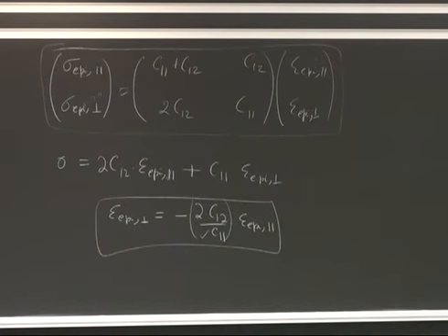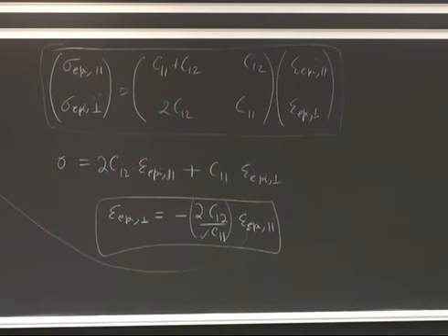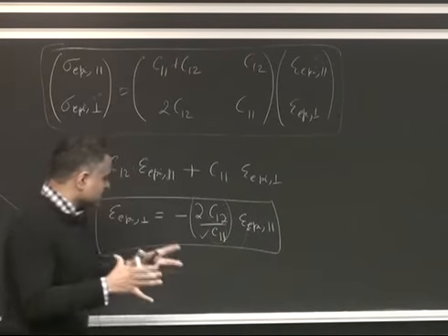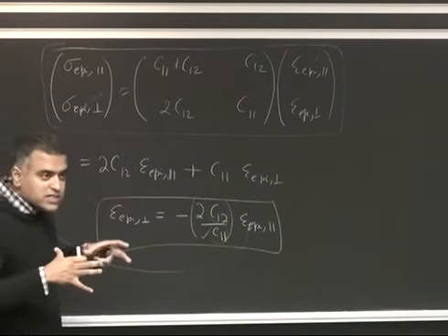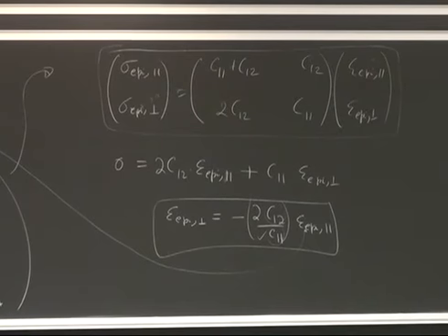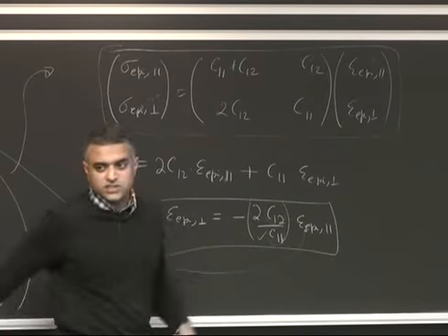Now this is something we know because we are trying to grow a certain layer of a certain lattice constant on top of another. So we know the in-plane lattice constant, the in-plane strain. Is that clear? So what we did, relating it to experiment, these are macroscopic parameters. People take the crystal and actually strain it and see how much force is necessary. They put it under diamond anvils or water pressure, and pressurize it and see how much it deforms. That's really the experiment that's being done. And these are your spring constants in the end. So we just made that connection there.